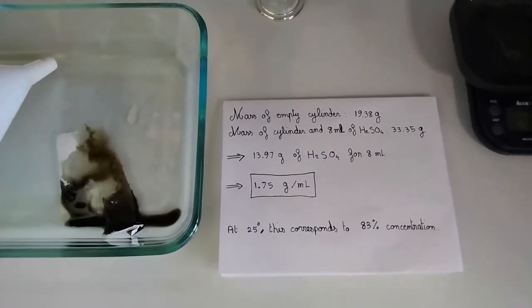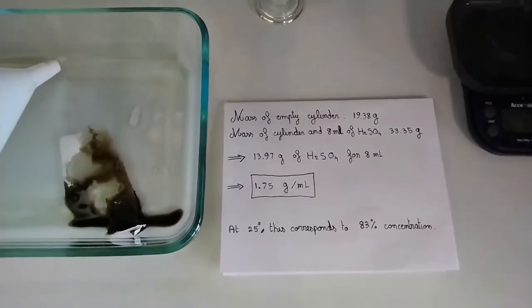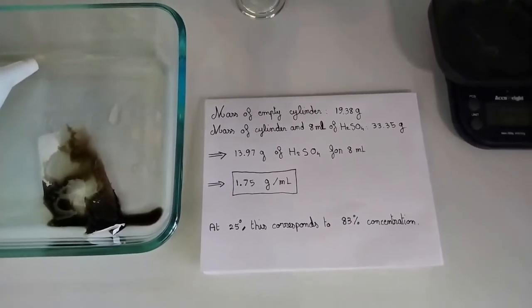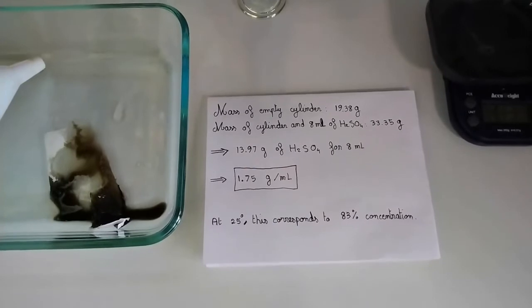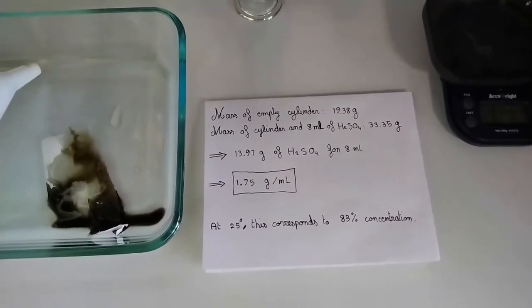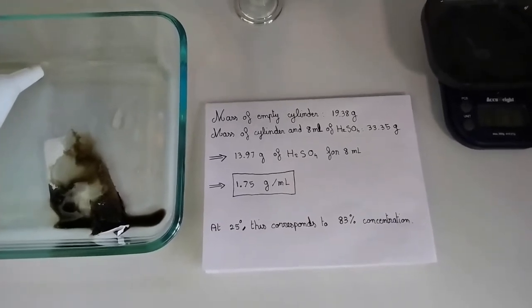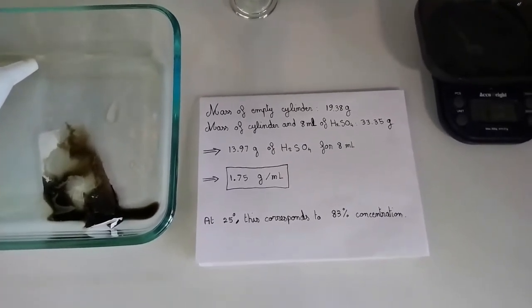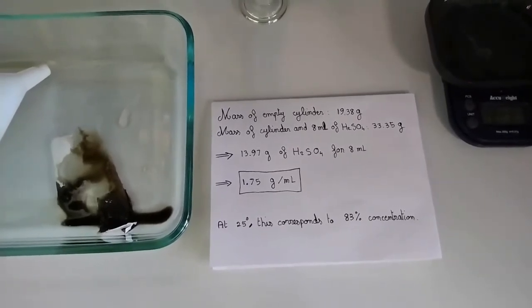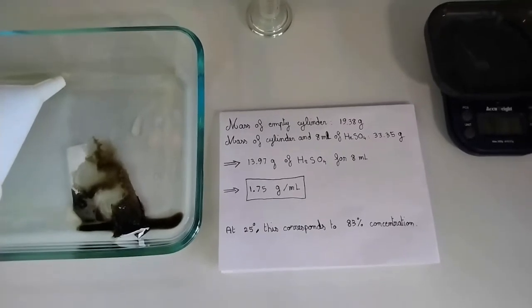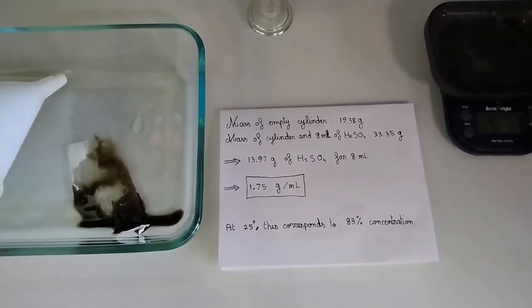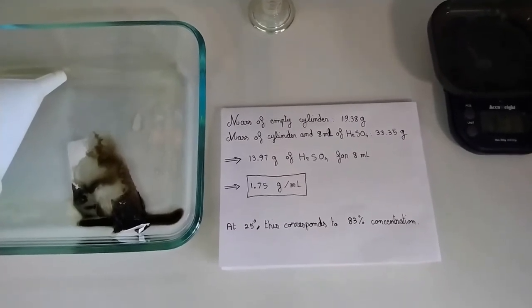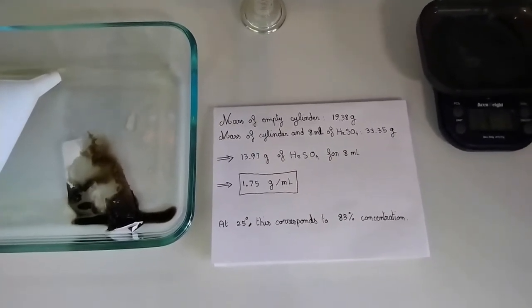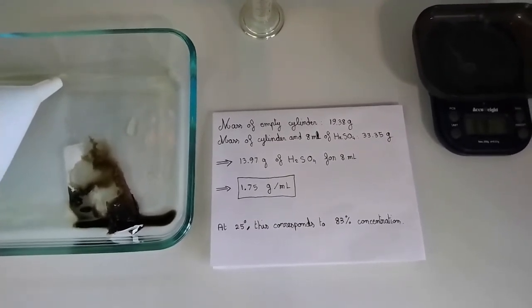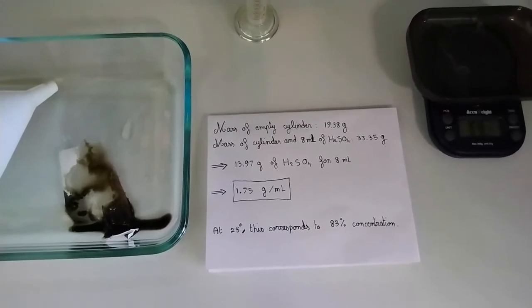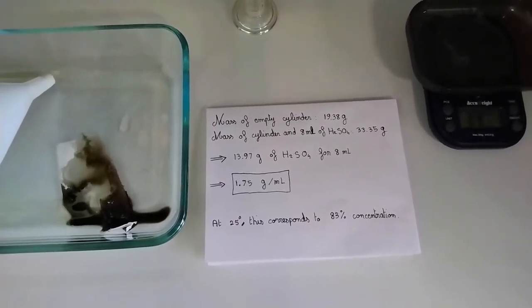So the mass of the empty cylinder was 19.38 grams, and the mass of the cylinder with 8 milliliters of sulfuric acid was 33.35 grams. So that means that the mass of sulfuric acid is 13.97. And that means that we only have to divide by 8 in order to obtain the density in grams per mil. So that's 1.75. And currently the temperature is 25 degrees Celsius. If you look online, you will find tables that indicate that a mass density of 1.75 grams per mil corresponds to a concentration of 83%.